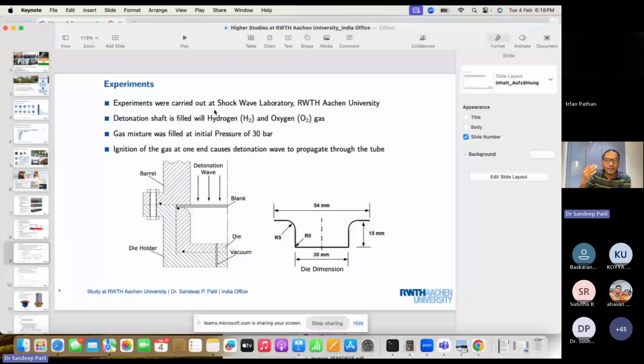In order to have high pressure on the detonation side, once that pressure is created, it can break the diaphragm. That means the diaphragm is providing the time to create that amount of pressure. Once a certain pressure is reached, it breaks the diaphragm, and then the detonation wave travels and hits the blank. Depending upon how much pressure you are applying, it is getting into shape here. For our experiment, we wanted a cup formation.